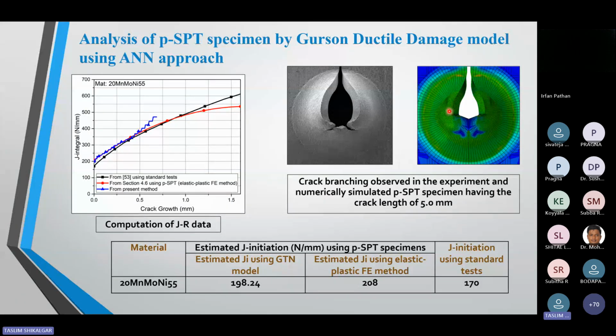The next task is to find out the crack growth. For each CTOD, how much is the crack growing? So I added one Fortran code in Abaqus so I can get the Gauss point coordinates. Any element has 4 to 8 Gauss points, and my small code gives me each Gauss point's coordinates. So I know the initial coordinates and the final coordinates, and with each increment I can tell how much the crack is growing.